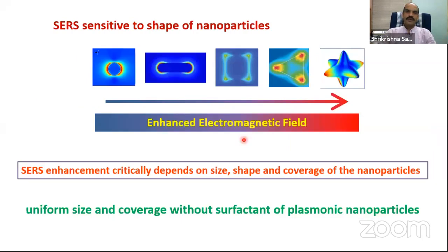Another aspect is that if you are having spherical nanoparticles, again this is the simulation, you can see that this red color is everywhere around the metal nanoparticle surface. But if, for example, these two nanoparticles are merged, let's say 4 or 5 nanoparticles are attached and form this nanorod, what will happen now? The enhancement will occur only at these edges. If it is cubic or triangular, you can see that these red regions are not everywhere on the surface. So the hot spot will be only here and here and here. For the star shape, this will be only here, and so on and so forth.